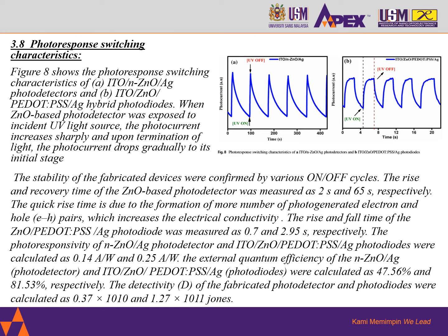Now, photo response switching characteristics. Figure 8 shows the photo response switching characteristic of the indium tin oxide/zinc oxide/silver photodetectors and indium tin oxide/zinc oxide/PEDOT:PSS/silver hybrid photodiodes. When the zinc oxide based photodetector was exposed to the incident ultraviolet light source, the photocurrent increased sharply, and upon termination of light the photocurrent dropped gradually to its initial stage. The stability of the fabricated devices was confirmed by various on-off cycles. The rise and recovery time of the zinc oxide-based photodetector was measured as 2 seconds and 65 seconds respectively.